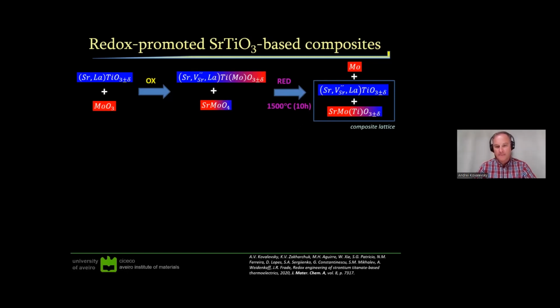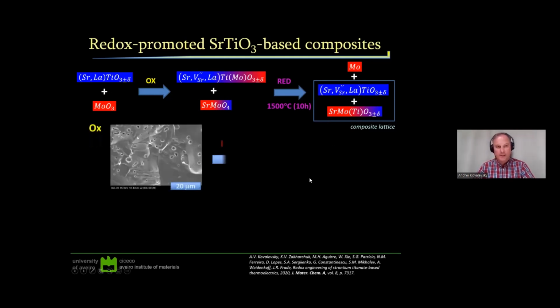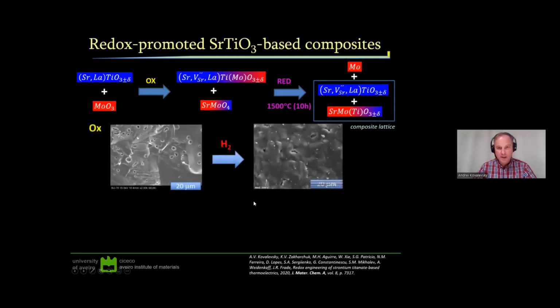of such a composite containing the matrix itself, based on strontium titanate, then some part of strontium molybdate perovskite, and eventually molybdenum submicron and nanoparticles. So here you can see the microstructural evolution which happens in this case.